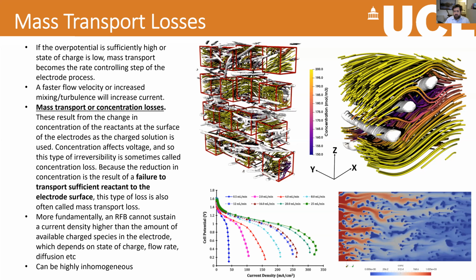And this can be really tricky in flow batteries for a variety of different reasons. Firstly, because we have these complicated 3D structures in our electrode through which the electrolyte flows, and also because we have a changing state of charge over the course of, for example, a discharge of the battery. And so as we go to a higher state of discharge, a higher percentage of our reactants have actually already reacted. And so our electrolyte per volume contains a much diminished amount of reactant. And so when we're at lower states of charge, actually demanding these higher current densities is quite tricky.